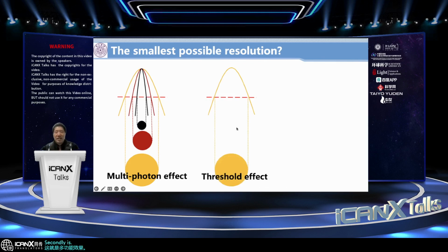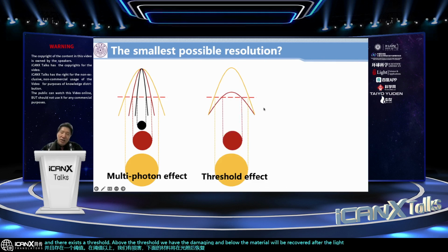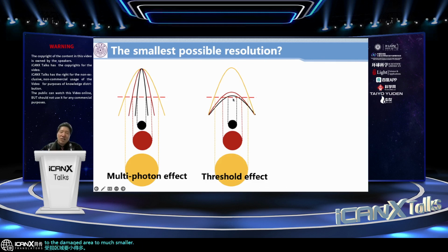Second is the threshold effect. It means it's also a kind of nonlinear effect. It means the laser damaging area does not always follow the laser focus spot size. There exists a threshold. Above the threshold, we have damage, and below it the material will recover after the light excitation. Then actually, if we reduce the light intensity, we can reduce the damaged area to much smaller than the optical diffraction limit.